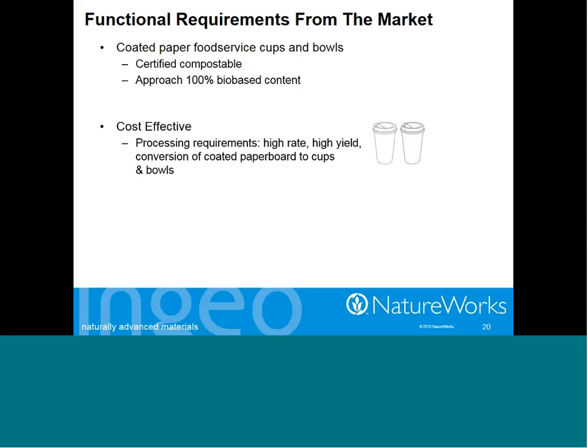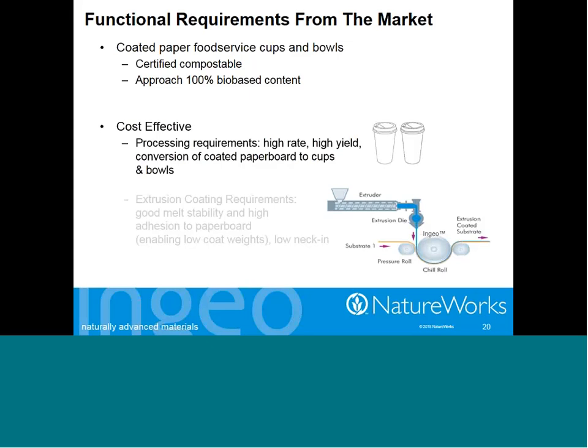From the cost-effective point of view, there's a couple of points here. The material needs to be able to run at competitive speeds to somebody making a paper cup with polyolefin. And the extrusion process has to be stable and work well. And there are some trade-offs between the cost of the goods, what you pay for the cup, and what you pay for the disposal. So in a typical venue, there would be some waste hauling fees, and if your material is 100% compostable, you can often trade your garbage hauling fees for some composting, where the composter isn't going to charge you quite as much to pick stuff up, or may not charge you at all. So this would be an example where the compostable nature of PLA would provide a benefit over a polyolefin.